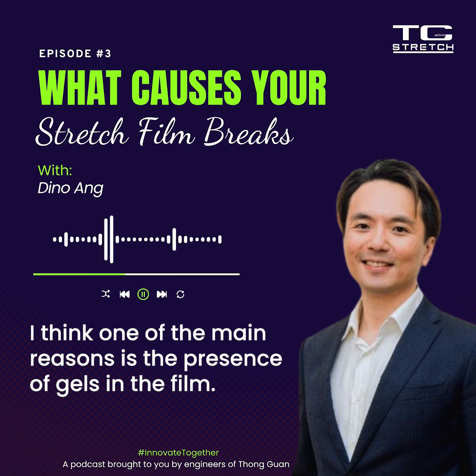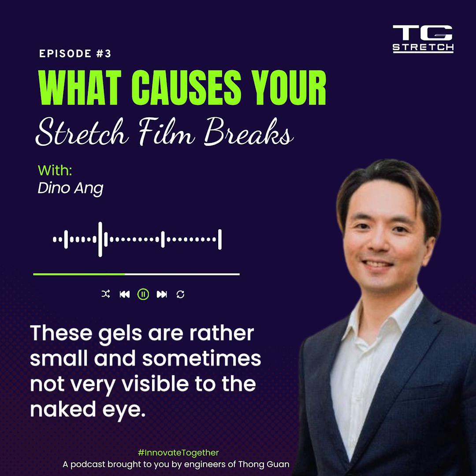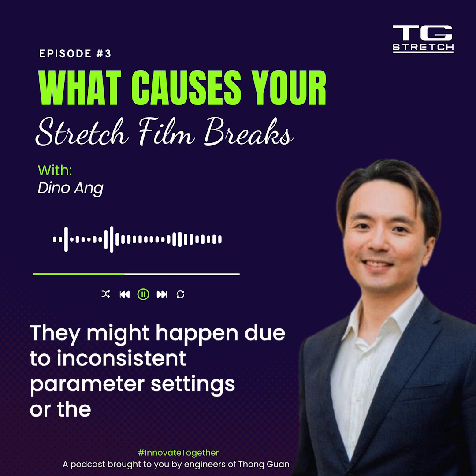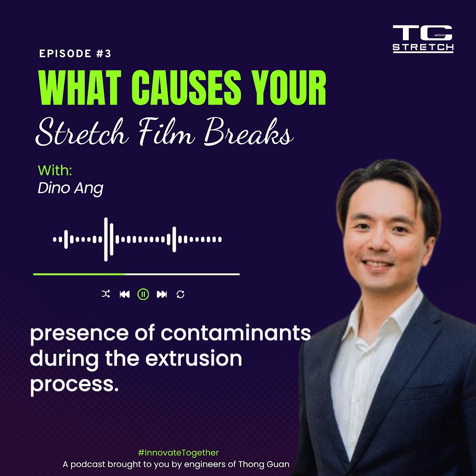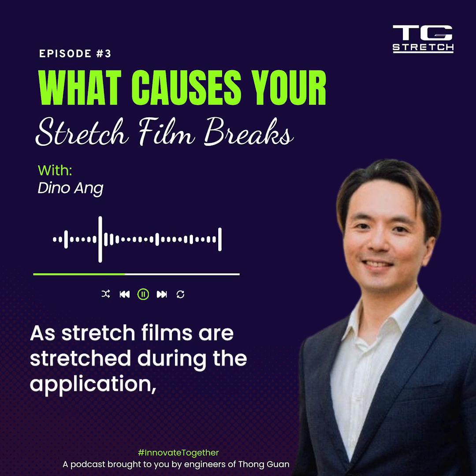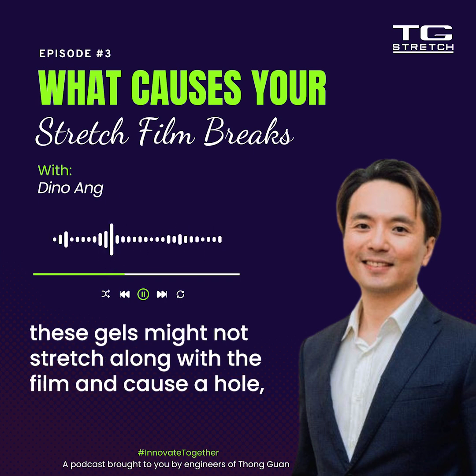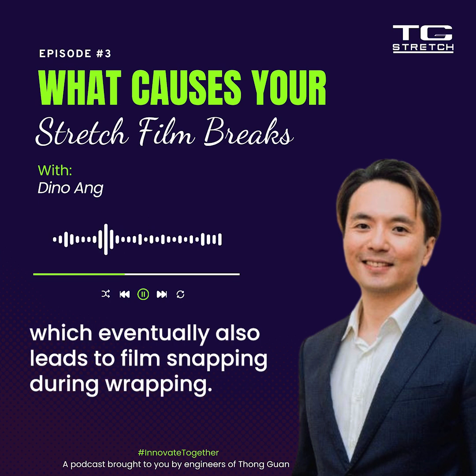I think one of the main reasons is the presence of gels in the film. These gels are rather small and sometimes not very visible to the naked eye. They might happen due to inconsistent parameter settings or the presence of contaminants during the extrusion process. As stretch films are stretched during the application, these gels might not stretch along with the film and cause a hole, which eventually also leads to film snapping during wrapping.